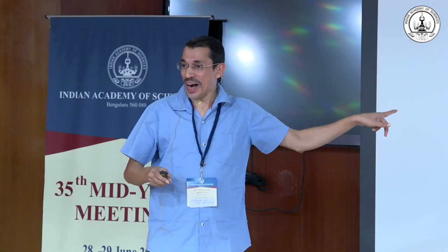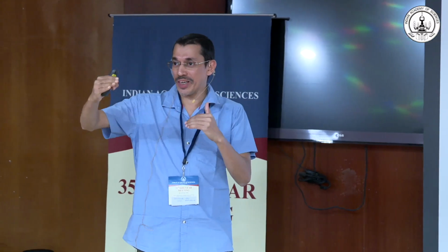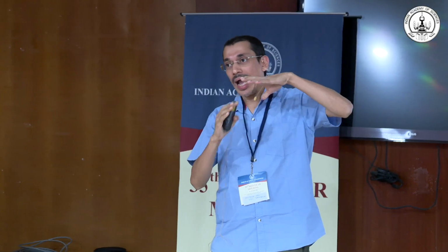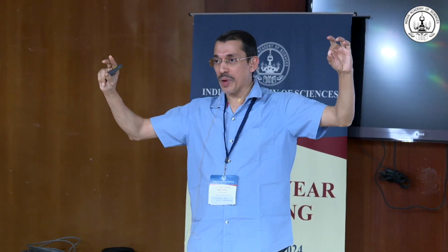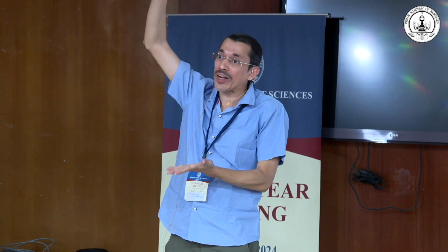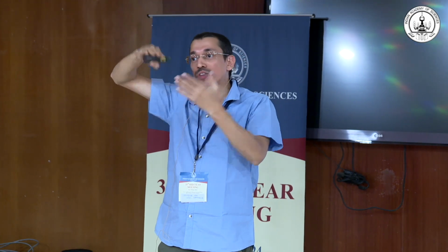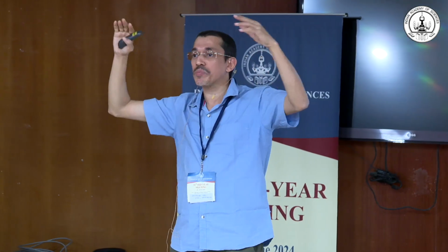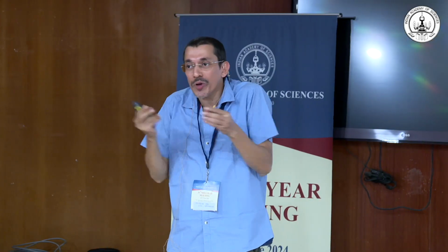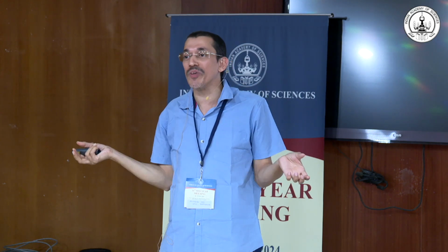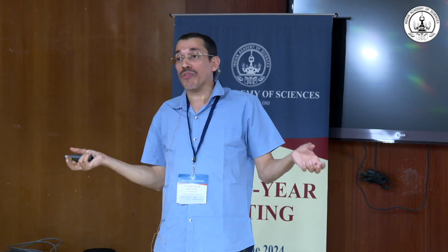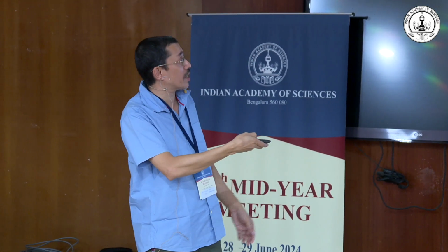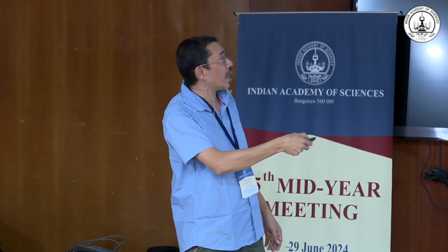So that was the second part. This is low temperature, then there is an intermediate temperature. The problem is at high temperature, because as I told you, there is an isolated flat band, but there is a higher energy band. So at very high temperature, the higher energy band also starts contributing. Eventually, at very high temperature, the system looks graphene-like, because you don't see the physics of the flat band anymore. If it was an isolated flat band, that would be my second part. In fact, in some intermediate range, you can see the impact of the physics of local moments.